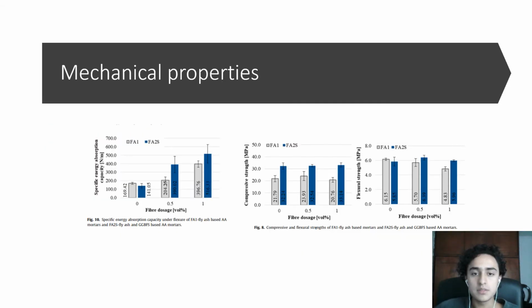Mechanical properties. It was evident that when implementing natural fibers, the compressive strength decreased due to the fact that the porosity increased and the density decreased, and the contribution to the tensile strength is minimal. In the graphs, you can see how certain properties increase or decrease for different samples according to the fiber dose.